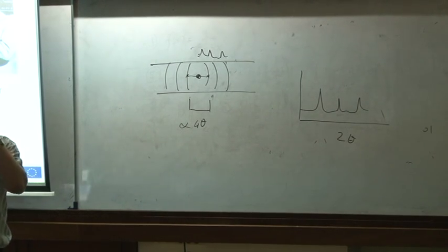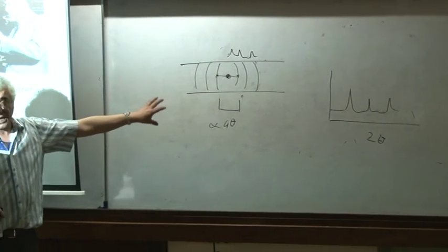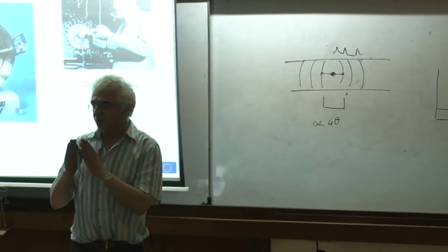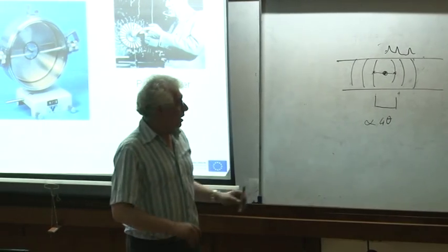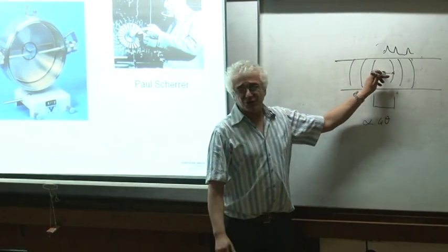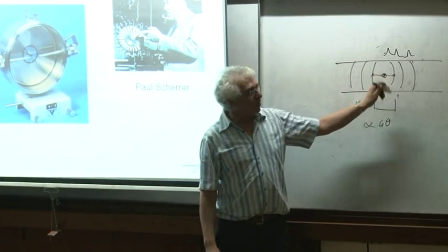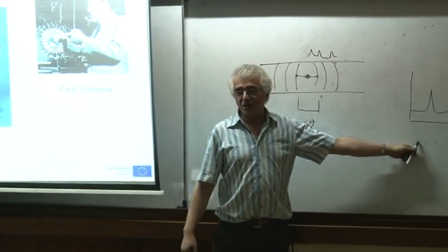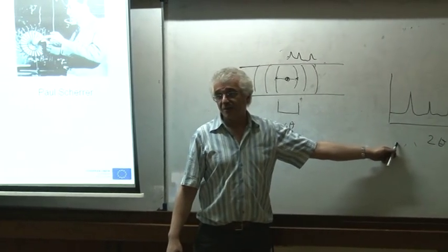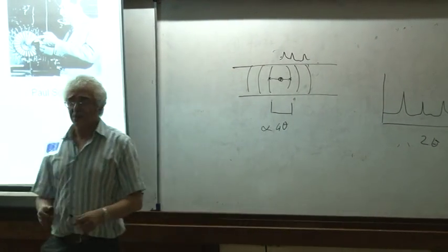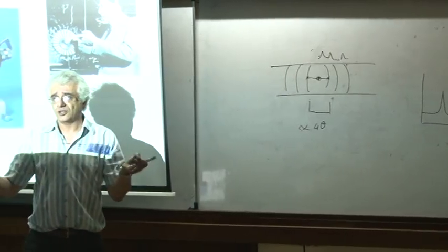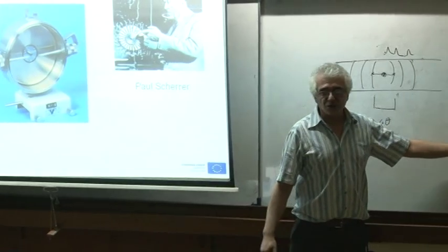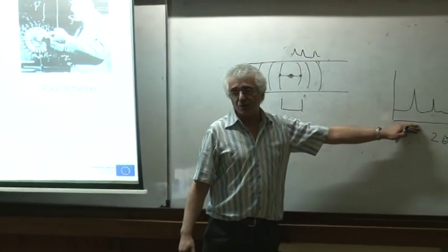The other problem with this type of camera is that the resolution is actually quite poor. It takes about 24 hours to get a really good pattern, whereas I can collect one of these on a modern diffractometer in about 20 minutes for a nice pattern. So that's the difference. The diffraction theory is identical. You should be able to see everything on here that you do here, but here it will be better resolved.